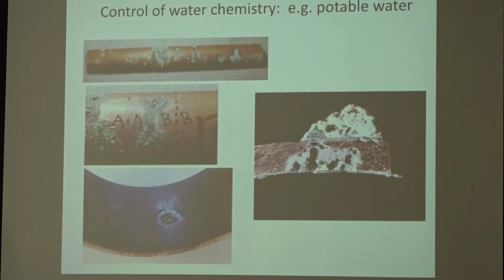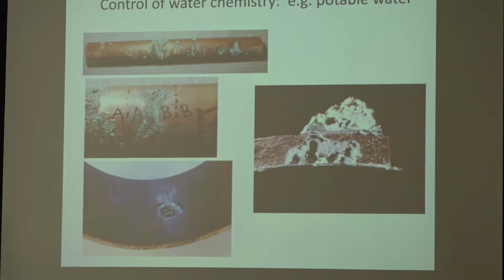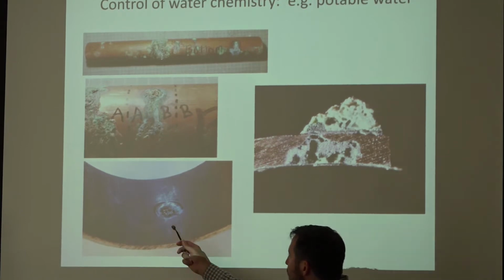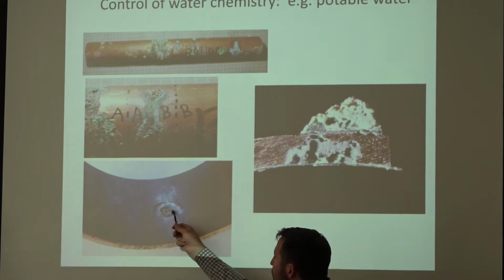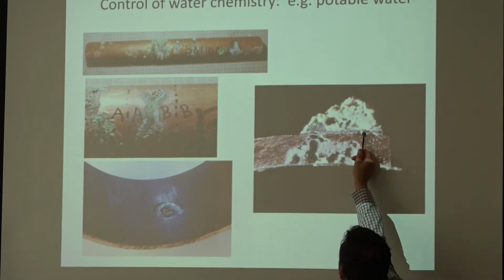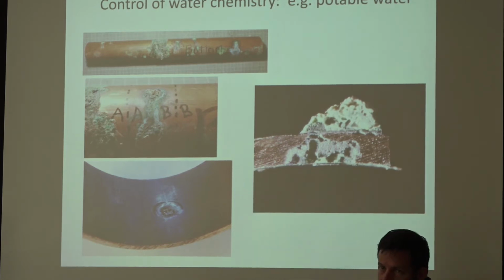So to start corroding copper, you break down that protective layer on the surface. What you can see here essentially looks like drilled holes. There was a little bit of a deposit here. There was a big buildup. So the outside of that location is built up just like you see in the image.